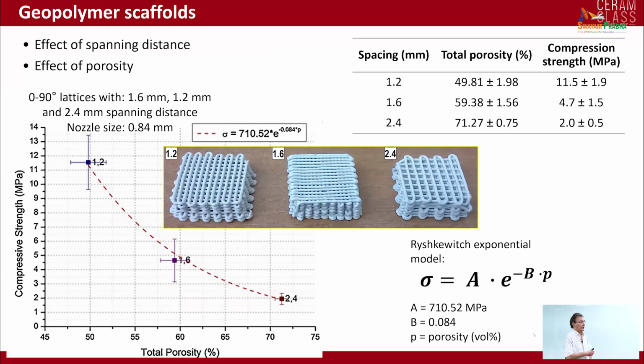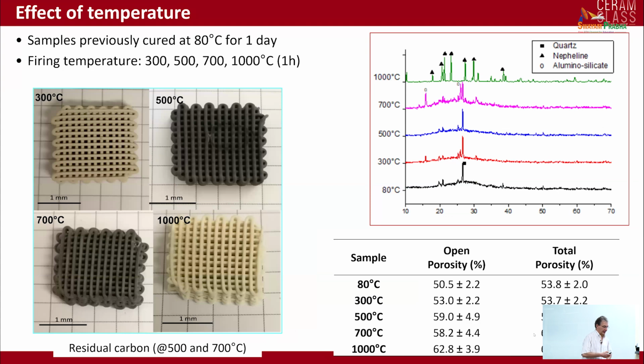And here we want to simply investigate the effect of total porosity on the strength of the structures, materials with the same morphology. And you can see that, of course, by increasing the porosity, you reduce the strength.